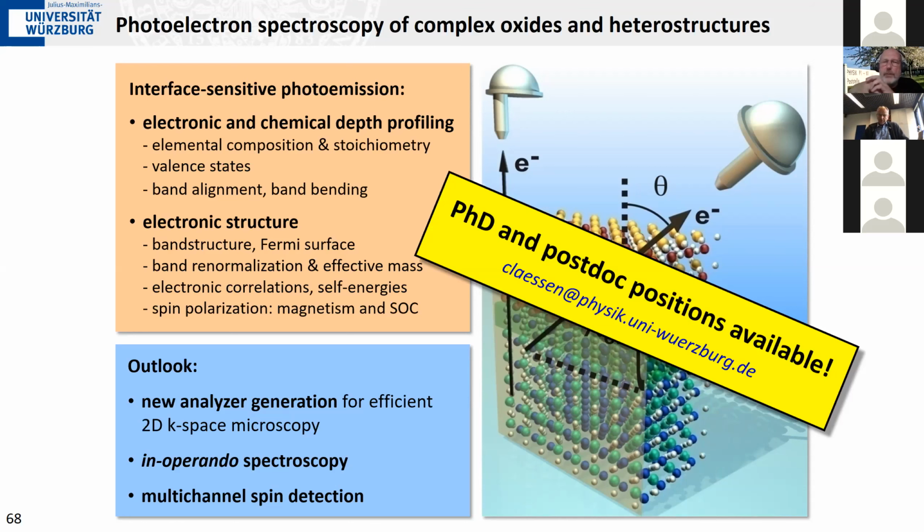If you try to interpret it, you have to be very careful. Very often people interpret X-ray absorption in terms of unoccupied density of states. Yes, exactly. Which is not correct, especially not in 3d transition metals, because you have very strong excitonic effects. So you cannot neglect the many-body effects that you have in there.